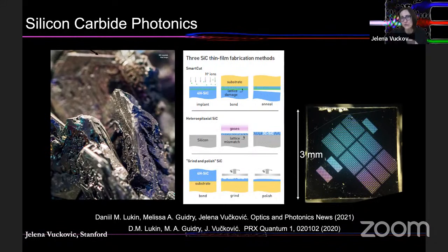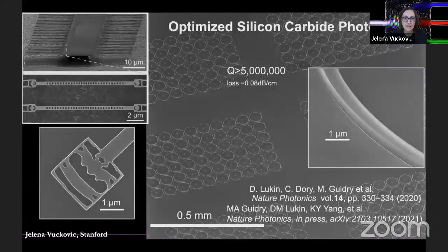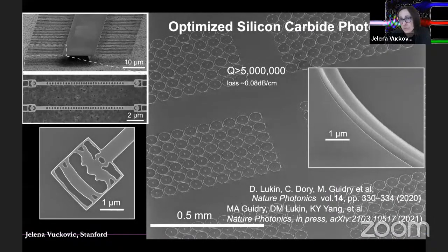And this method is also scalable to wafer scales, although that's not something that my graduate students would be doing at Stanford, probably in industry. So with this approach, we're actually able to make very high quality photonics. At the moment, we have quality factors of resonators in the near infrared exceeding 5 million and loss of 0.08 dB per centimeter, right? So this is comparable to lowest loss photonics. It's actually lower loss than silicon photonics. It's almost as good as silicon nitride photonics made at EPFL and IBM, which has a record low loss.